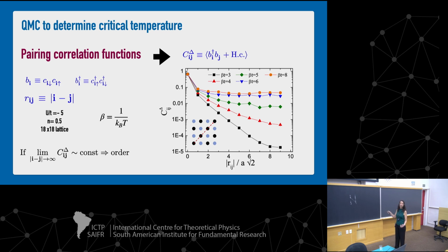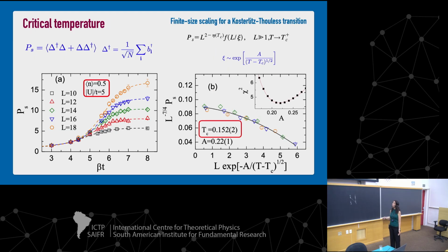If you're very hot, let's say it falls very quickly. If you're not very cold, but cold enough, it stabilizes, and it means you're forming pairs, and your pairs are correlated along your lattice. And we use this to probe the critical temperature.